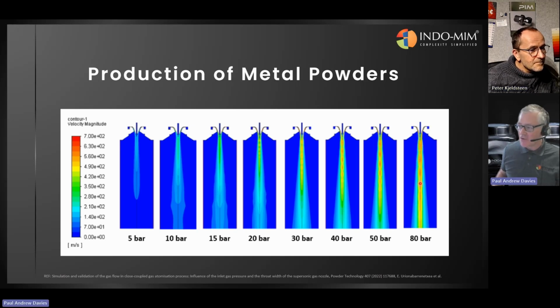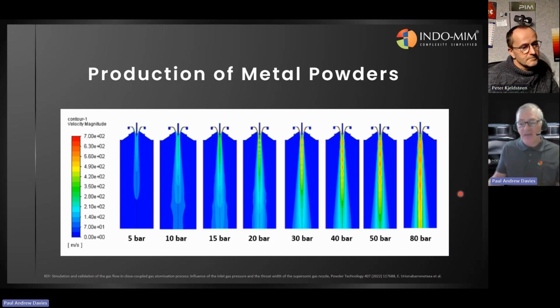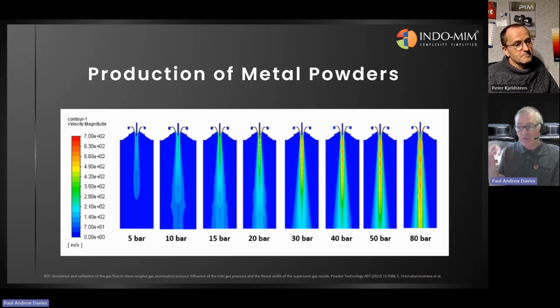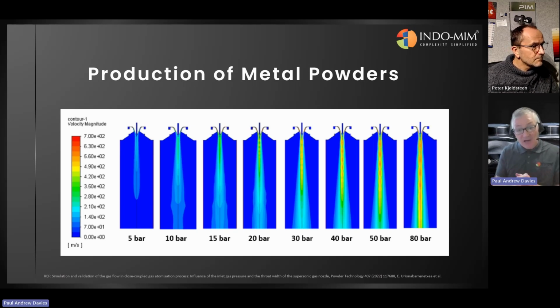Exactly. So there's a number of different shock waves forming, and no doubt a dead zone just below the atomizing tip as well, and that can have an influence on the drawing of the molten material into the atomizer. So you want it to be effectively sucked into the atomizer and then fragmented and atomized. So controlling the gas and modeling different atomization designs has now become a little easier by using computational dynamics modeling, as you see here. So you can model the gas, and then it gets even more complicated by modeling the gas as well as its interaction with the molten material. So you have two-phase computational fluid dynamics, and that takes a lot of computer power.